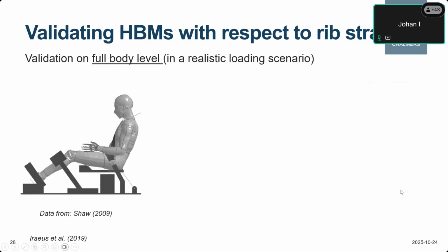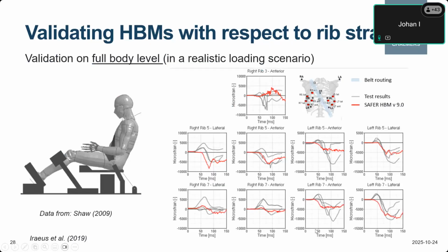And then finally, there are a few full cadaver tests with more realistic boundary conditions. This is Shaw 2009, also one of the HBM for VT tests, where we have a belted occupant without any load limiter. In this case, they had 4 strain gauges on each side, and we could compare the traces from the cadavers in gray with the simulation result in red. And again, there is a wide spread in the cadaver tests, and I would say that we do a decent job here at least, but it's really hard to say if it's perfect or not.